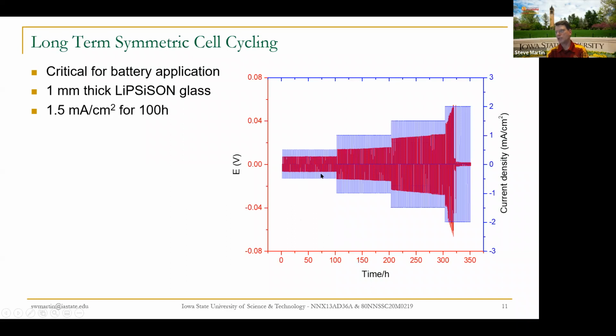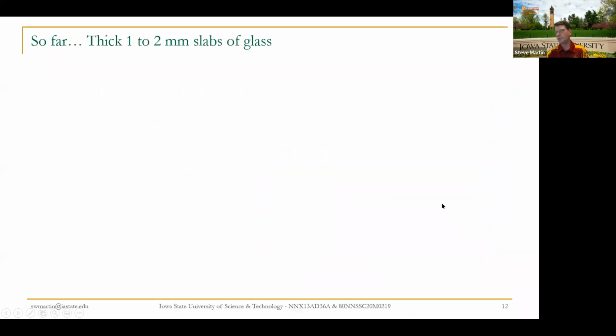This just shows that we can cycle the battery back and forth, back and forth. But eventually when we push it too hard, here we've abused the battery because we want to see where it would fail. It fails out here at about 2 milliamps per square centimeter. Your cell phone operates at about 1 milliamp at maximum. Cars operate at about 3 milliamps of ionic current per square centimeter of electrolyte. So we're getting very close to even automobile level performance.